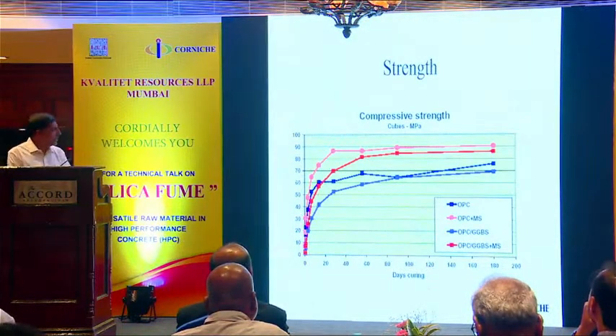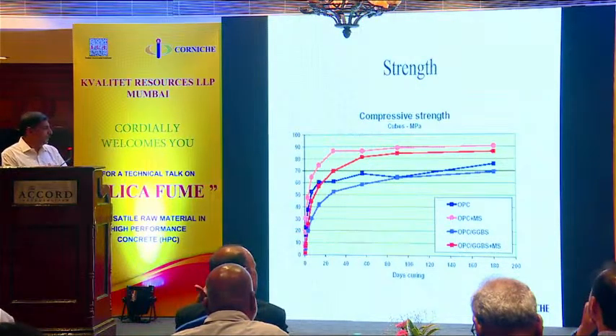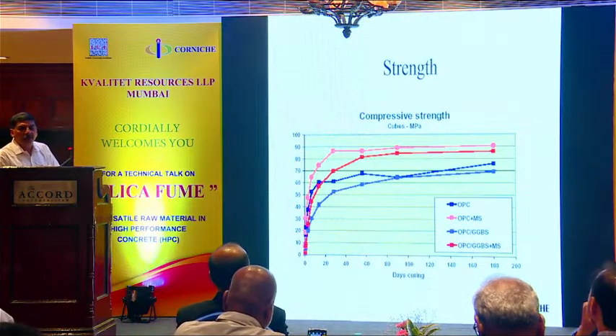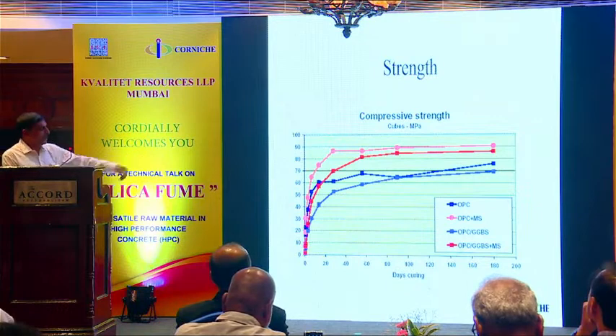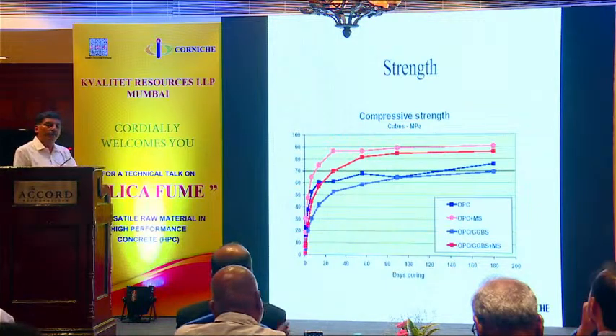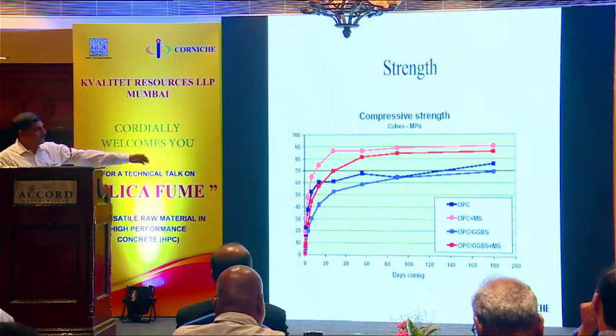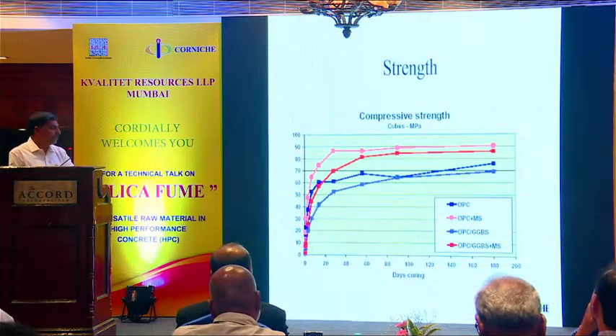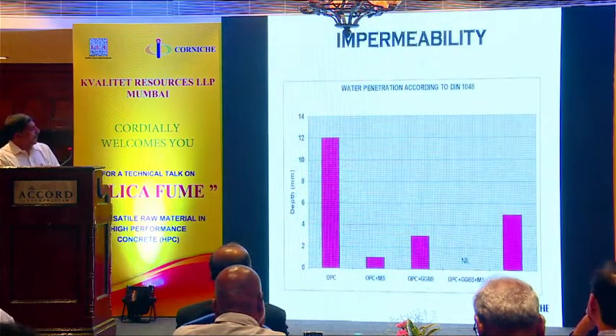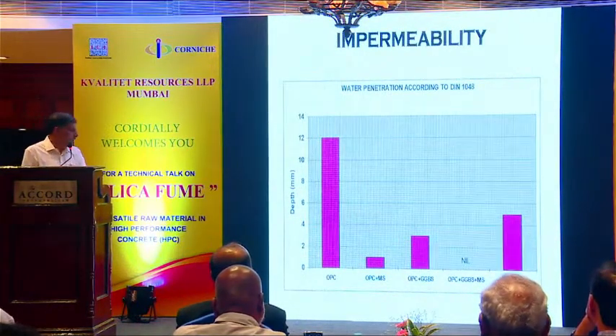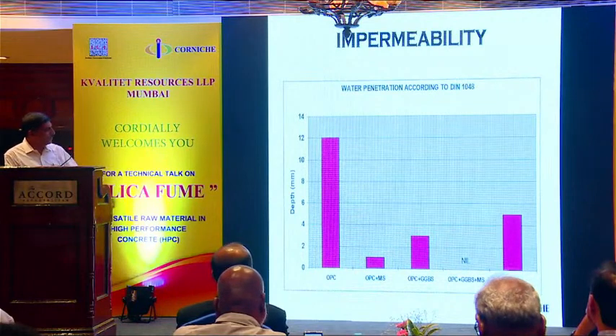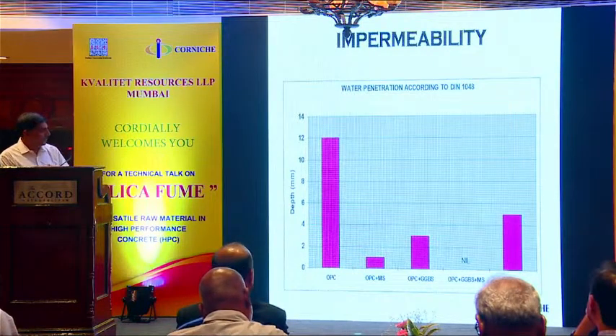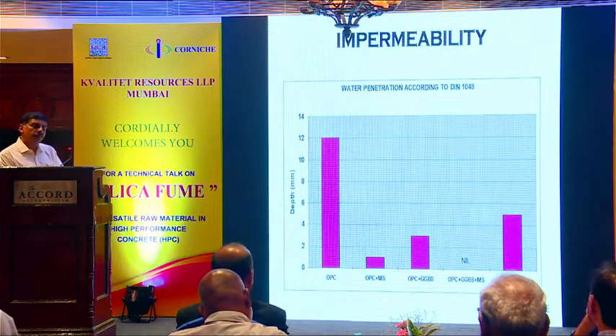And strength, if you see, in silica fume concrete, you are able to achieve the desired strength in the first 7 days itself, minimum 80%. And ternary blends, triple blends are the best, even better. Here I've taken OPC, GGBS, silica fume. It will be a similar pattern with OPC, fly ash, and silica fume. And impermeability, you see, OPC and add silica fume to it, how it becomes highly impermeable. And again, the ternary blend is the best.